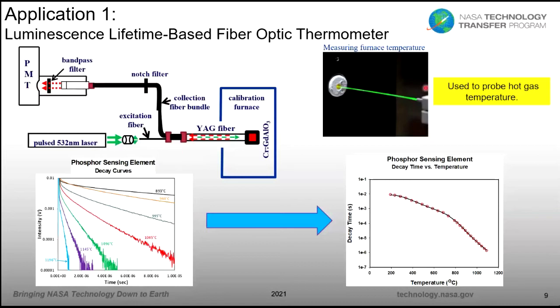Here's just a photograph. This is one of the larger fibers. I picked the larger one because it takes a better picture. You can see the green 532 nanometer laser light going through it. The sensing end is inside that furnace. Okay, we can then collect our decay measurements at different furnace temperatures. And here you can see it's pretty sensitive to temperature.